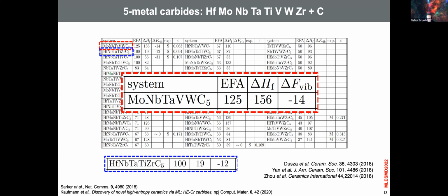All right, but look carefully at the top 2 systems. Actually, we start from the second one, which is this one. This one has hafnium, niobium, tantalum, titanium, zirconium carbide, right? This was discovered by some of our competitors a couple of months before us. Here are the references, and you see it has a lot of entropy gain and very little enthalpy loss. This is kind of obvious. In fact, those are experimentalists, and the reason why they did this is kind of obvious, because hafnium carbide is cubic, niobium carbide is cubic, all precursors are cubic, are already rock salt.